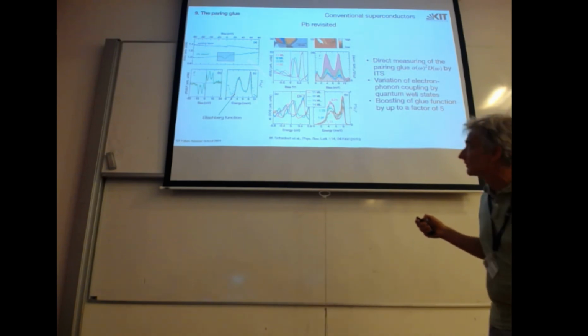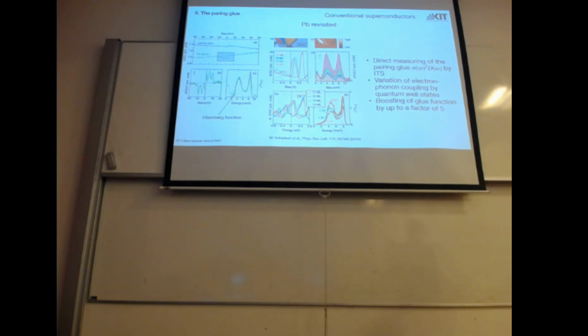It's not perfect, maybe due to energy resolution, or to be honest, this is not exactly what happens, because with STM you don't tunnel to all of the states with the same probability, but mostly to the states which have a forward tunneling direction, so there's a little bit of weighting, and also maybe the matrix element is Q dependent. But in this simple approximation, the match is really nice. So our claim at that time in this PRL was that we can measure directly the Eliashberg function.